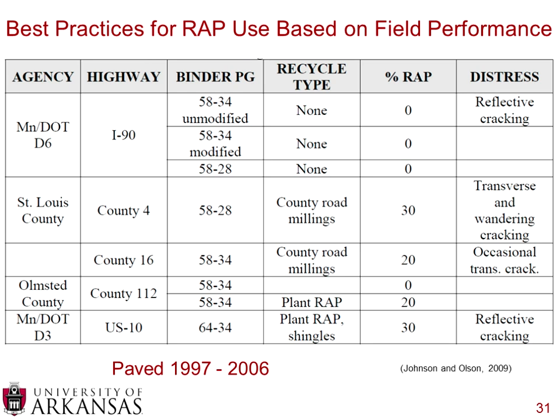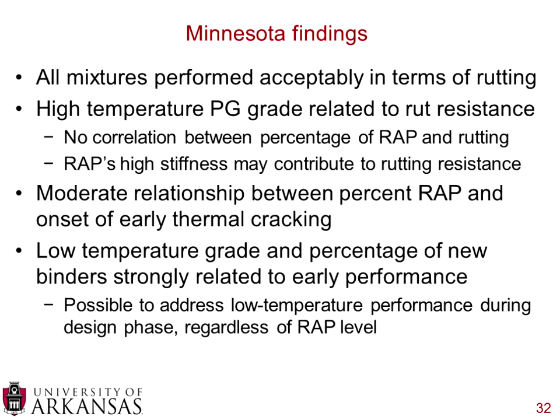Of interest here in this Minnesota report is that they've got a couple mixtures here in the high RAP content, around the 20 to 30% RAP content. And you can see these were paved anywhere between 1997 and 2006, and this report was performed in 2009. And overall, they found that all mixtures that contain RAP performed acceptably in terms of rutting. They found that the high temperature PG grade was related to rut resistance. So while there was no correlation between the percentage of RAP and rutting, they did find that the high stiffness of the RAP asphalt cement may contribute to rutting resistance.